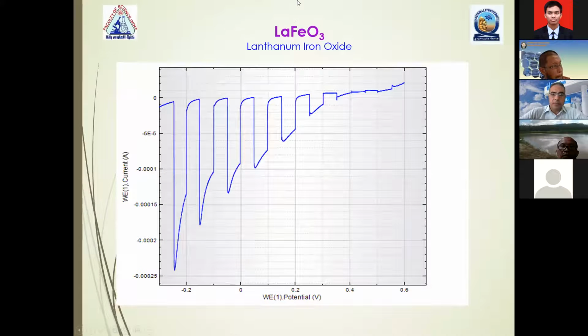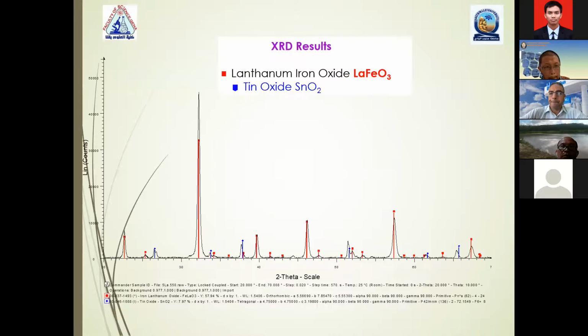This is a photocurrent response, which means it's photoactive and can be used for a solar electrode. The same XRD shows the same structure, lanthanum iron trioxide, which is lanthanum iron oxide, with these peaks in red, and the blue one is tin oxide, which is mainly found in the glass, so it's not important.